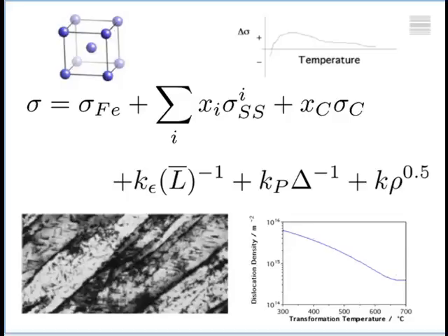If our material contains crystals which are shaped like this, like plates, then the finer I make the plates, the stronger our steel will be, because you put lots and lots of barriers in the way of plastic deformation. So the strength will vary with 1 upon the thickness of these crystals. If these are not plates, but they are crystals which are of the same size in all directions, then we have the classical Hall-Petch effect, where the strength will vary with 1 upon the square root of the crystal size. So the finer you make the crystals, the stronger your steel will be. And I'll come back to that point later on in the lecture.